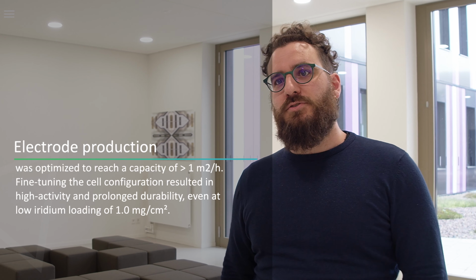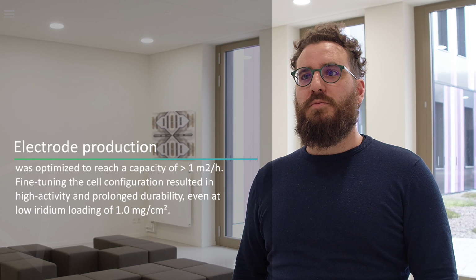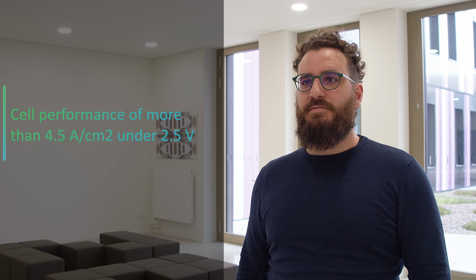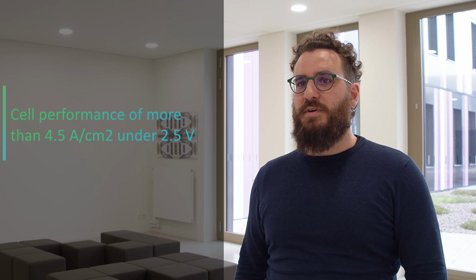Fine-tuning the cell configuration resulted in high activity and prolonged durability, even at low iridium loading of 1 milligram per square centimeter. The second generation of the CRM-reduced catalysts demonstrated a cell performance of more than 4.5 amps per square centimeter under 2.5 volts. The electrolysis stack was assembled with the optimized cells, totaling 1,000 square centimeters of active area. The stack was then sent to HiCenter for testing.